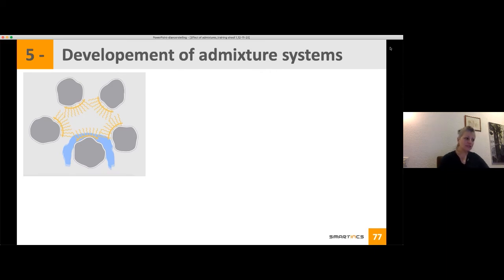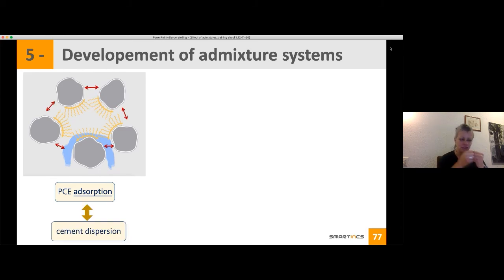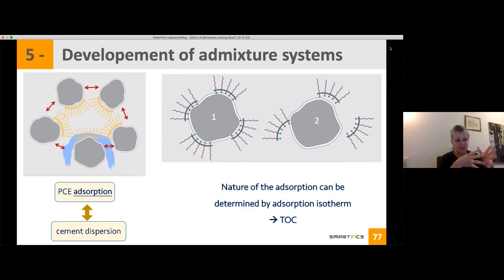So to come to the TOC, I mentioned in the first part of the presentation the adsorption of the PCE. So how much will, how you say, come onto the surface of your cement. This is directly correlated with the dispersing effect of your PCE. So we have a method, the TOC, to measure how much is adsorbed on your cement. And then that gives you an indication: are you in situation number 1, where what you put is nicely adsorbed on your cement particle, or in situation 2, where you have a cement particle, but your admixture for some reason doesn't really attach to it, or doesn't provide a dispersing effect? So in that sense, you will have more incompatibility with your cement.